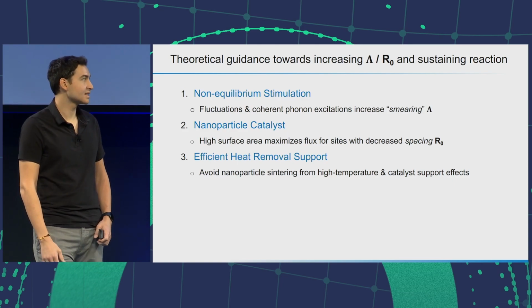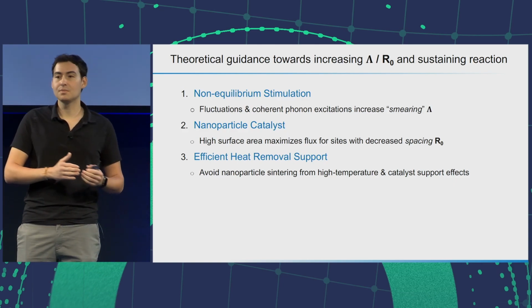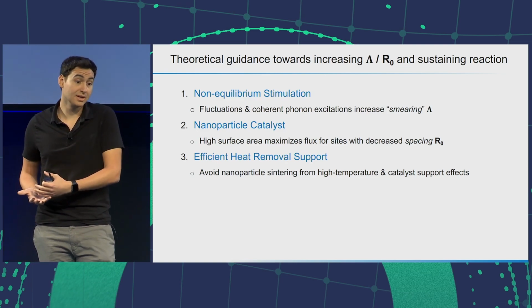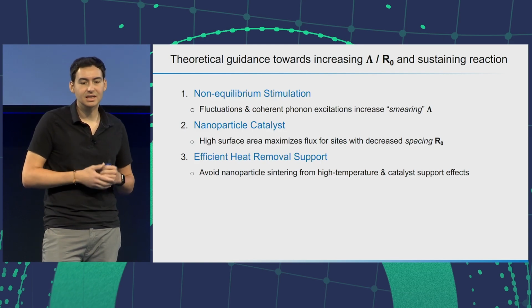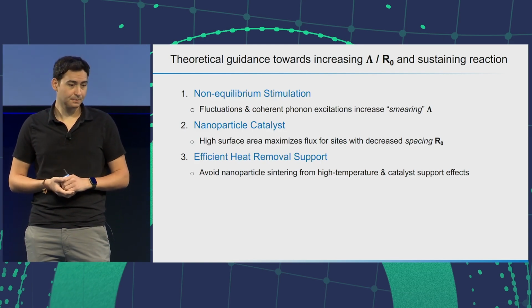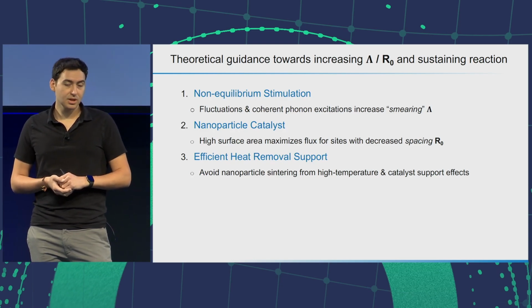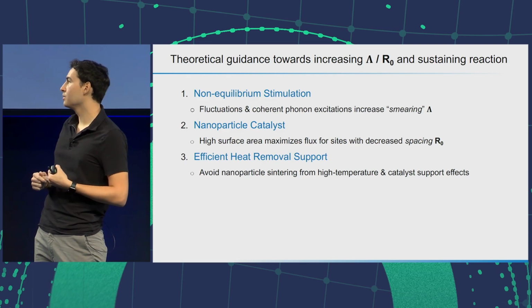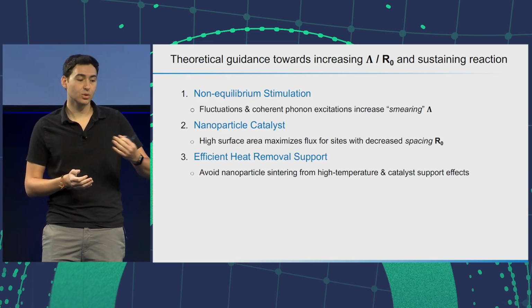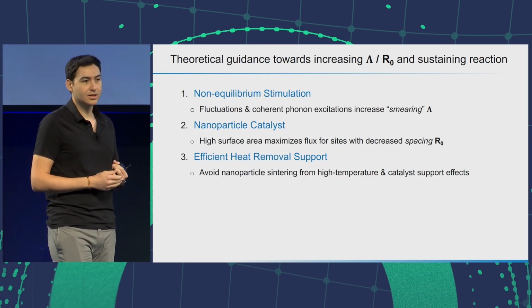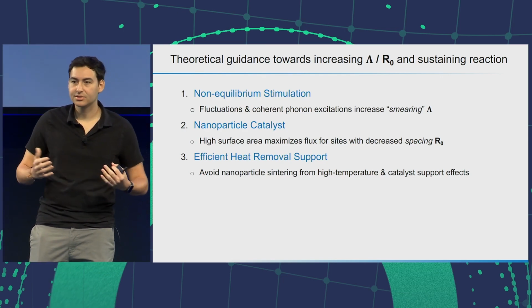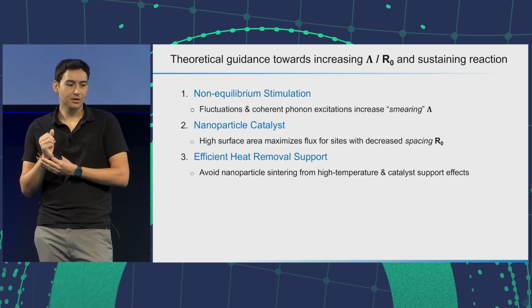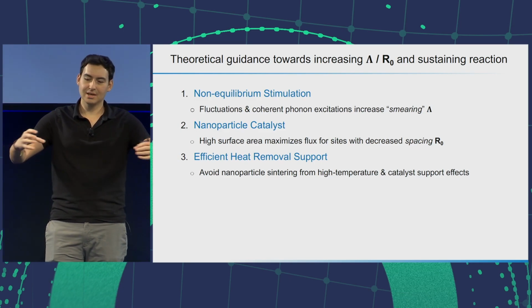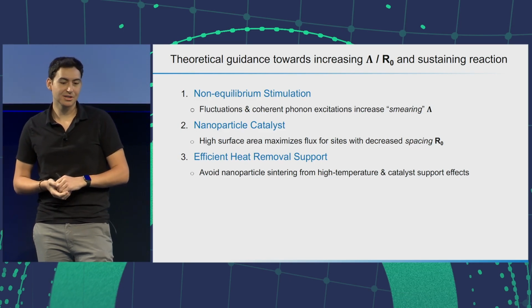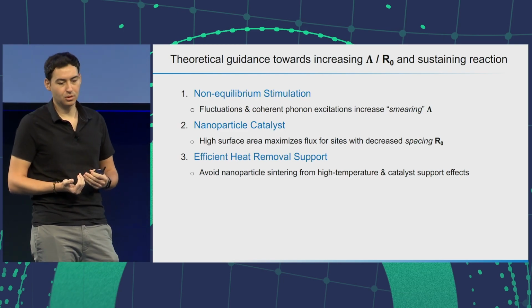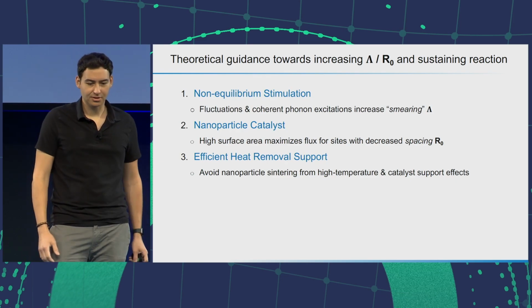And so with this in mind, we can ask, how can this theoretical underpinning help point us in a direction towards useful R&D and actually engineering a system? What can we learn from these insights, even if it's not a complete theory that explains everything? And so in that spirit, we came up with 3 components. One is this non-equilibrium stimulation. How do we kick the system out of equilibrium to enhance the probabilities? Two, we wanted to work with nanoparticles, a high surface area, to maximize the amount of flux going in and out. And then three, when you're dealing with nanoparticles, you don't want them to sinter. One comes to its neighbor and they form a big blob, and you lose the nanoparticle nature that you worked so hard to achieve in the first place. So how do you couple that to a support that won't be destroying the very nanoparticles you created?